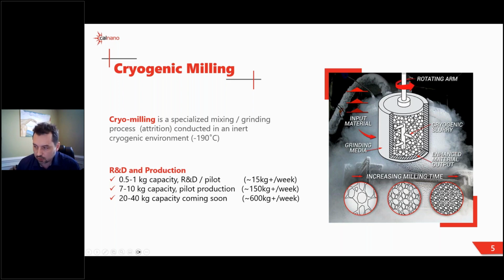So essentially here, similar to a drill press or a mill, you have a large torque and rotating inertia put into the system, which is then churning the grinding media. That media can be made out of anything from stainless steel to tungsten carbide or ceramics. In our case, we most often use stainless steel. And then the material that you're processing is in a liquid nitrogen slurry living in between all those bearings or that grinding media. Now, depending on the type of material, you're going to have different effects as a result of that. But that's the basic layout and setup of the system.